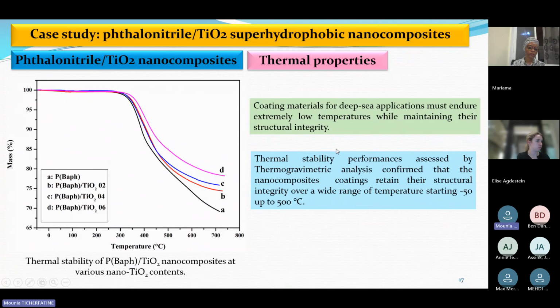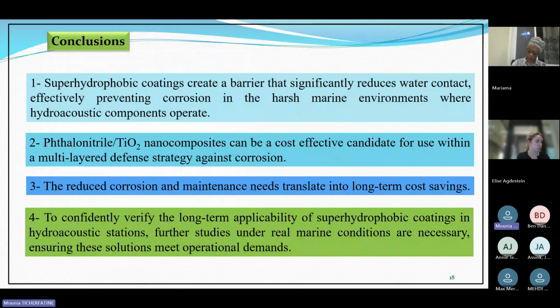So, to conclude, superhydrophobic coatings create a barrier that significantly reduces water contact, effectively preventing corrosion in the harsh marine environment while hydroacoustic components operate. Phthalonitrile/TiO2 nanocomposites can be a cost-effective candidate for use within a multi-layered defense strategy against corrosion. The reduced corrosion and maintenance needs translate into long-term cost savings. And to confidently verify the long-term applicability of superhydrophobic coating in hydroacoustic stations, further studies under real marine conditions are necessary, ensuring this solution meets operational demands.